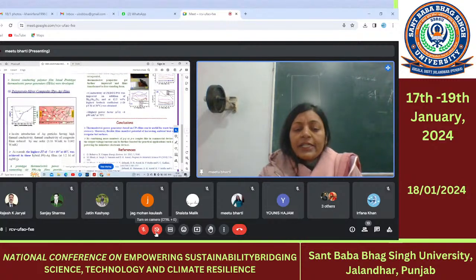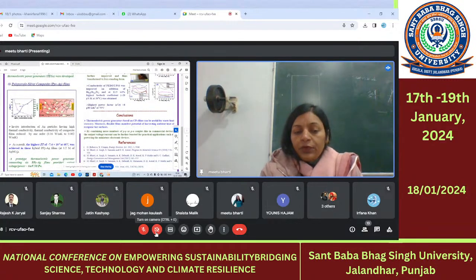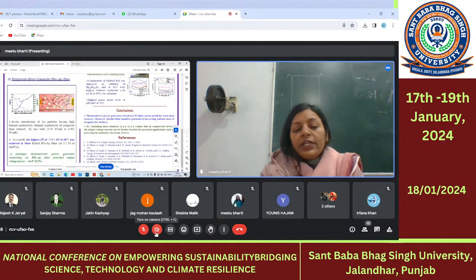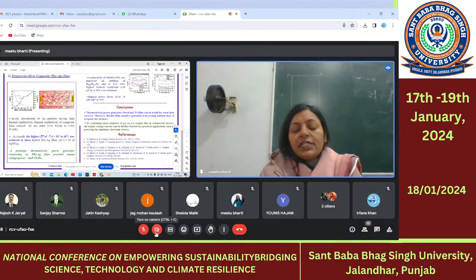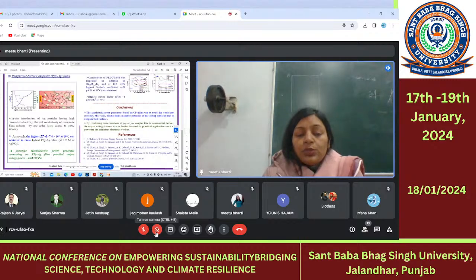As a result, the highest ZT, thermoelectric figure of merit, 7.4 times 10 to the power minus 3 at 60 degrees Celsius was obtained in these films. We also used 6 PPy-Ag strips, electrically connected in series and thermally in parallel, and this generator provided an output voltage of 6 millivolt or power of 30 picowatt when a temperature gradient of 65 degrees Celsius was obtained.